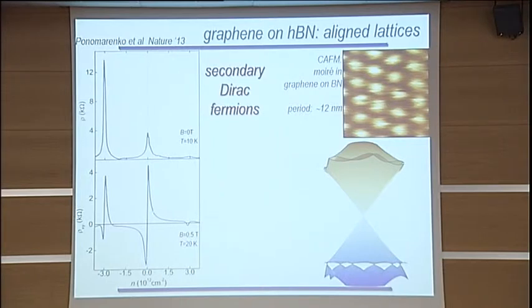Now what we basically do, we start with very well-developed hole conductivity here, so our transport is dominated by holes, and then suddenly RXY changes sign. It means that we now have electrons which carry charge, and then we get into hole conductivity again.